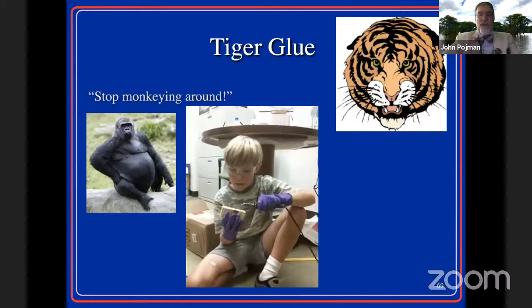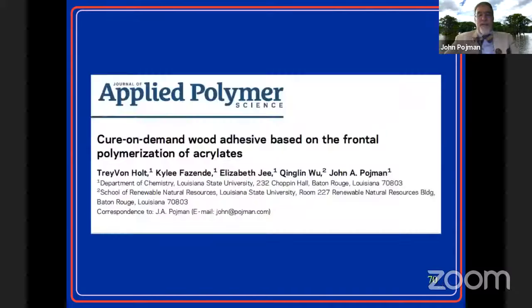So it does work. We were able to actually make a cure on demand wood adhesive. The problem is it doesn't work unless the layer has a minimum thickness of about 0.3 millimeters. So that kind of limits its application. It also has trouble working on systems that absorb heat well. For example, different types of wood have different thermal conductivities. And so that led us to saying we need to get better chemistry, more reactive chemistry. That's what we're studying now.